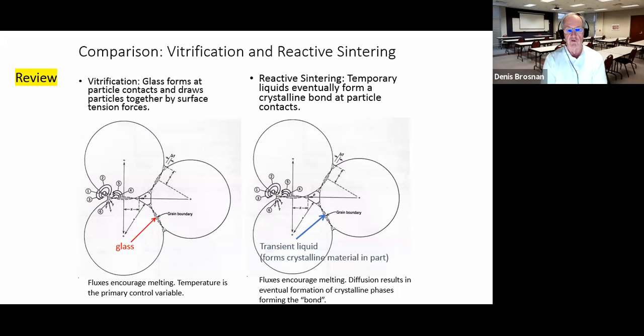So we'll review just a bit, 3 or 4 slides that we've talked about last time. Of course, we've talked about vitrification, and that's when we have particles and they form glass near points of contact, and we get these little sinter necks developing right at the points of contact. The driving force is to reduce the surface energy, and the glass migrates to these points eventually. The glass can be of a transient chemical nature and always approaches the final composition given on the phase diagram, but rarely ever gets there.